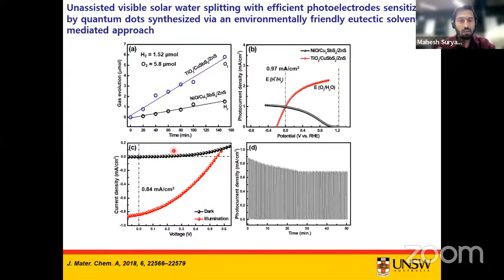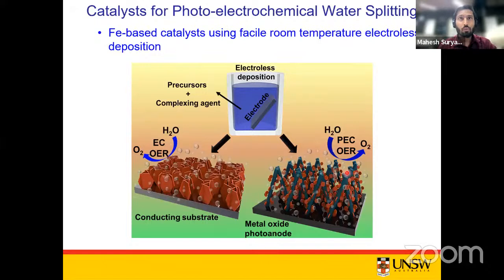We realized that every time we use sulfide based compounds or chalcogenides, we observe a decrement in the photocurrent density values. So we came up with an idea to stabilize these photocathodes or photoanodes. Of course, we mainly work on photoanodes. We have also worked on photocathodes, but I have not included those results here. So what is the approach that we employ? One way to further improve the stability is to load a catalyst, such as an iron based catalyst, on these photoanodes to improve the water oxidation kinetics as well as the stability.